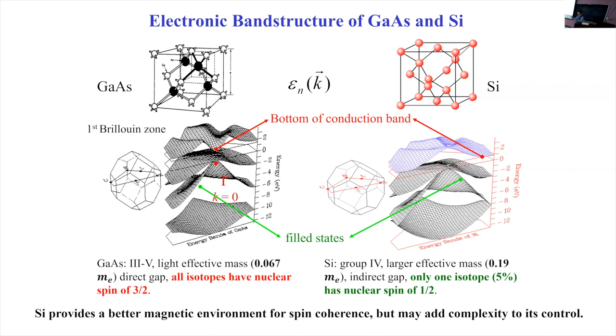Silicon is a little bit different. Silicon's valence band top is still at the gamma point, but its minimum of the conduction band is far away near the X point, about 85% out towards the X point along the 100, 010, 001 directions. So you have actually six equivalent conduction band valleys. They are way up there towards the X points. Basically, silicon gives you a very quiet magnetic environment for the spin qubit, but electrically, it could give you a little bit extra freedom, right?